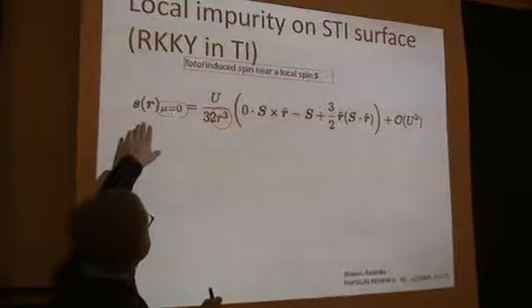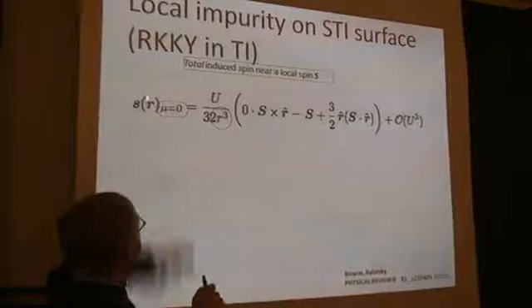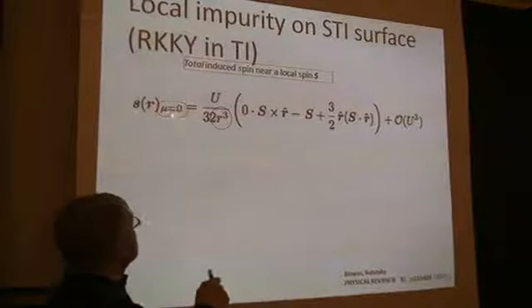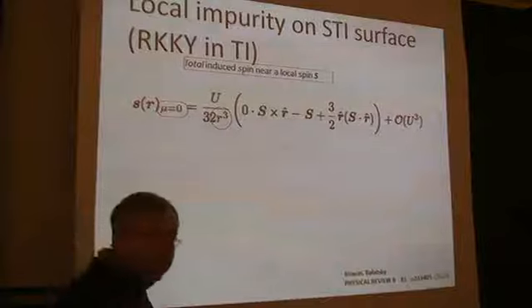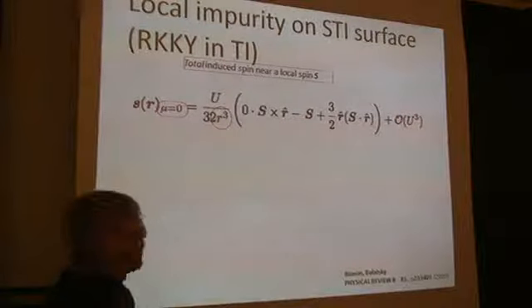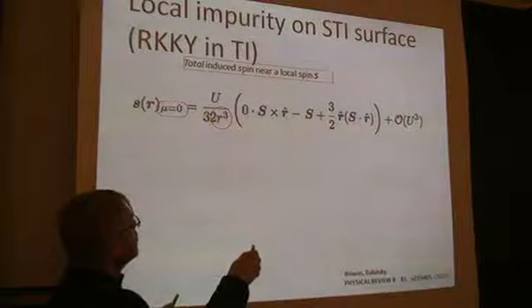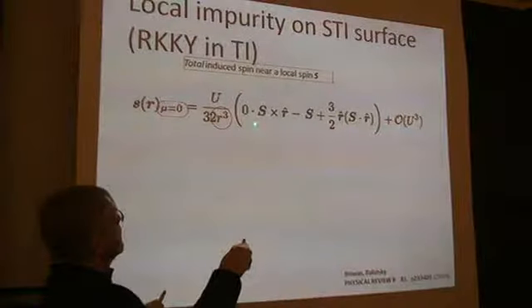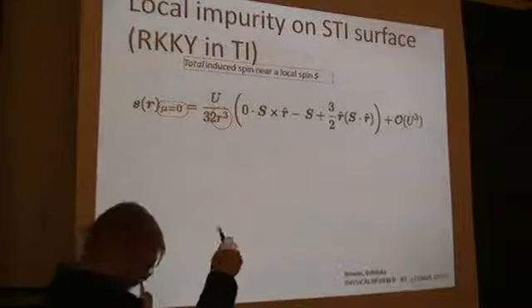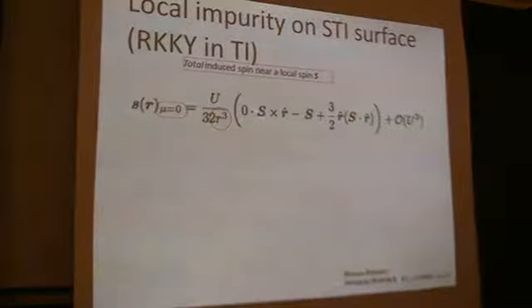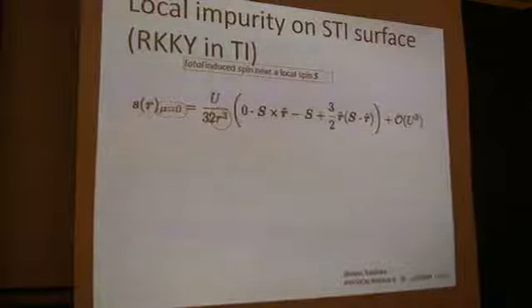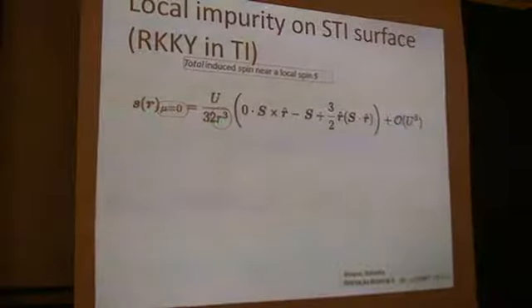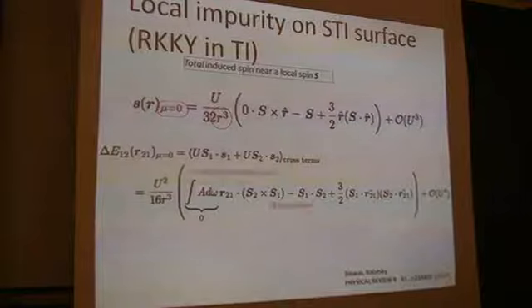So if you sum up all these single particle states to calculate the total spin density at distance r, in this case we take it to be at zero chemical potential, which is not realistic for the topological insulator as grown. It was just for the problem of a pure Dirac cone with this spin-orbit coupling. Then we'll see that there is the Dzyaloshinskii-Moriya piece that vanishes in the particle-hole symmetric case. Then there is the induced piece, which looks like it will be responsible for ferromagnetic coupling. And there is the dipolar piece. And they all die off with distance like 1 over r cubed.